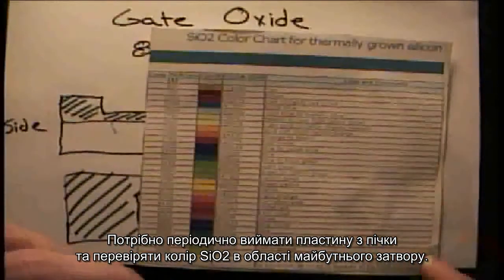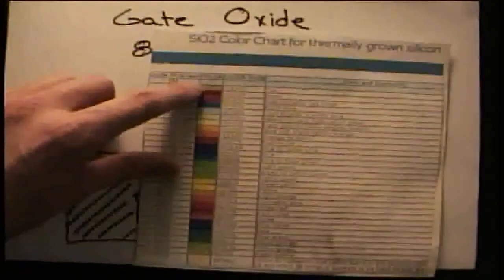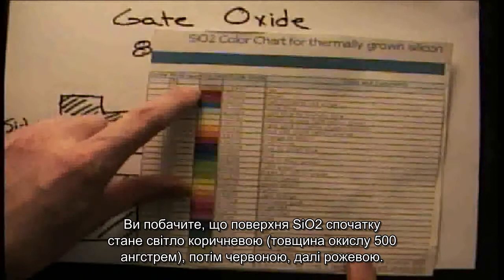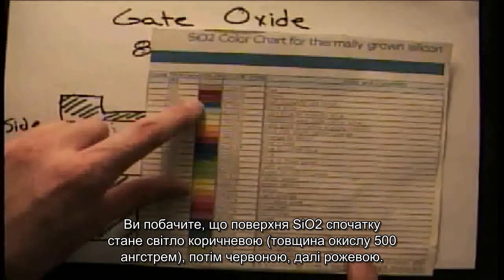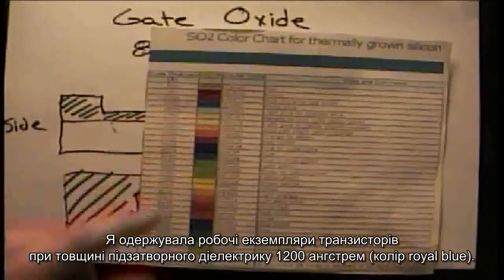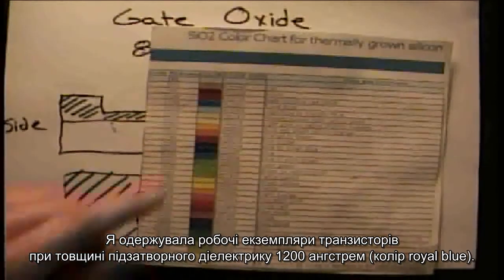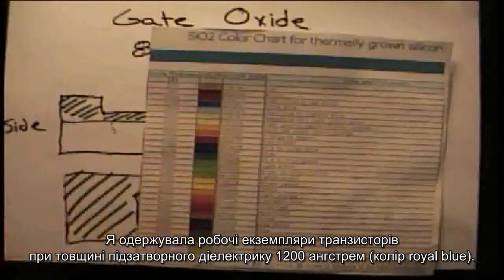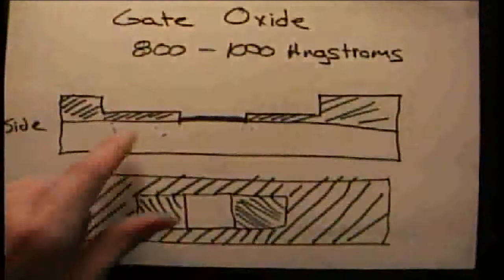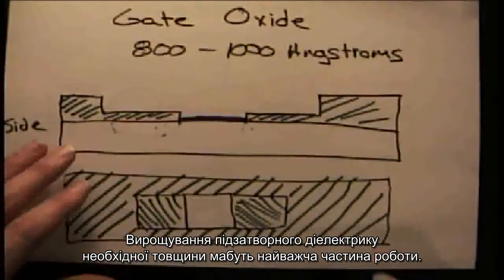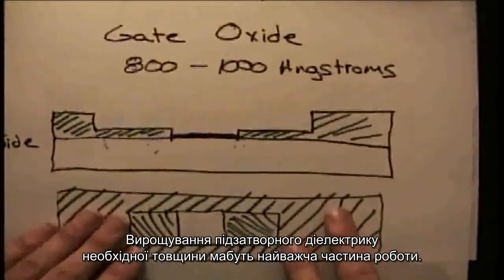And you'll have to pull it out of the furnace repeatedly and check. You'll see the tan color come in at 500 angstroms, and then it'll start turning red, and you'll shoot for pink. I've had successful devices that were this royal blue color, which is 1,200 angstroms. This is probably the most difficult part, is gauging the gate oxide.